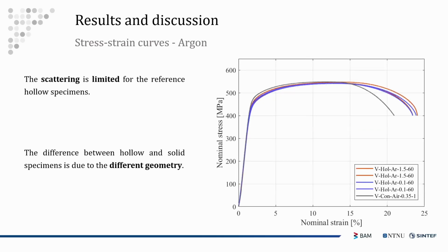On the other side, the stress strain curves obtained in argon, so the reference environment, show a very limited scattering for both the drilled and reamed specimens. So there is no substantial impact of the surface finishing when it comes to evaluating the tensile properties in an inert environment. While there is a difference for the solid specimen, that is mostly due to the completely different geometry we have in this case.